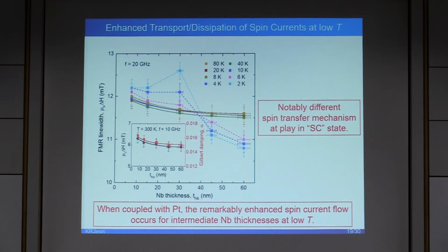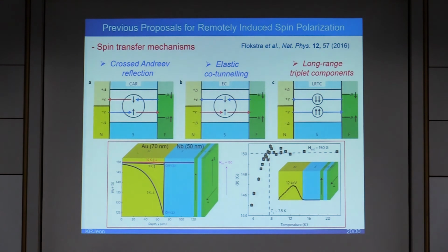We also note that for the intermediate niobium thicknesses, the FMR line width, and thus spin current flow toward the platinum layer, is progressively enhanced with decreasing temperature, not only in comparison with the other samples, but also in comparison with the normal state. The enhanced spin transfer cannot be carried by the quasiparticle current because we have already demonstrated that they are progressively suppressed with decreasing temperature below TC. Thus, the enhanced spin transport must involve superconducting current.